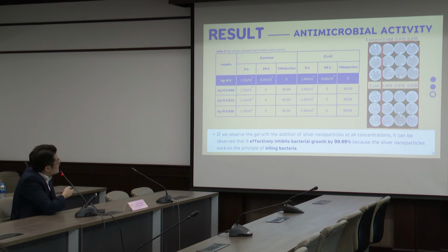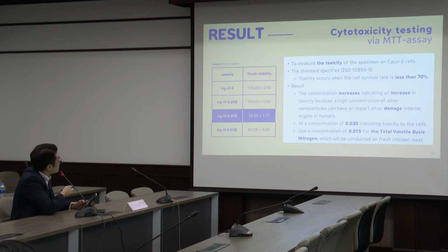And if we observe the gel with the addition of silver nanoparticles at all concentrations, it can be observed that it effectively inhibits bacteria growth by 99.99%, as you can see here. This is because the particles can encounter the cell membrane and also pass into the cell, where they can react with various kinds of molecules and functional groups inside, leading to inhibited bacteria growth and causing damage to the cell.